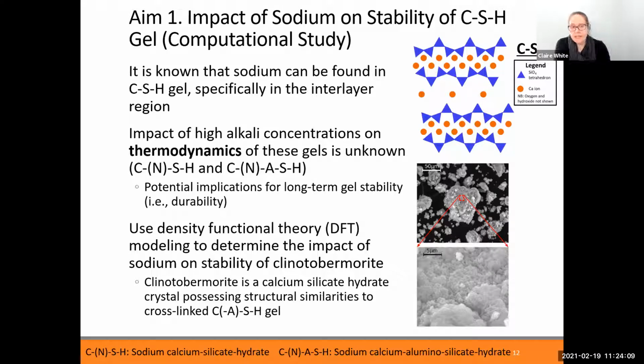And so what we did here was using density functional theory modeling to determine the impact of sodium on a crystalline model phase that's got very similar local bonding environments to calcium silicate hydrate gel. Because of the limitations with DFT, being able to get to really large system sizes, we know CSH is like a disordered nanocrystalline phase, but with the limitations of the system size, here we decided to model clinotobermorite, which has very similar local bonding environments to the actual gel,